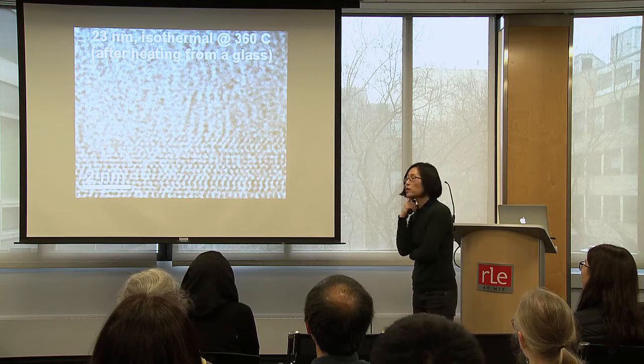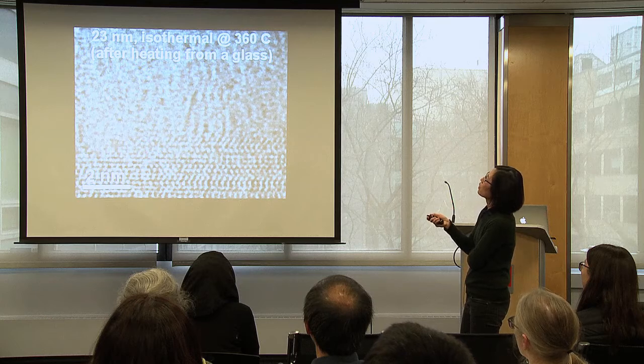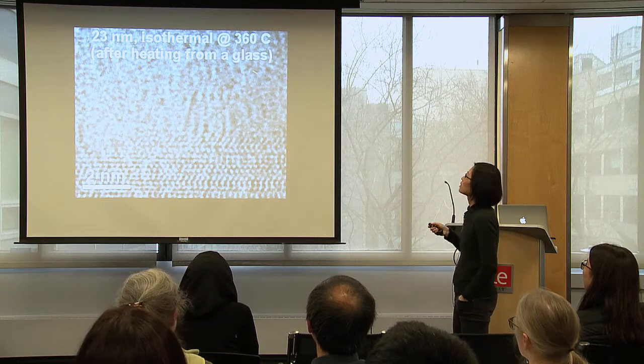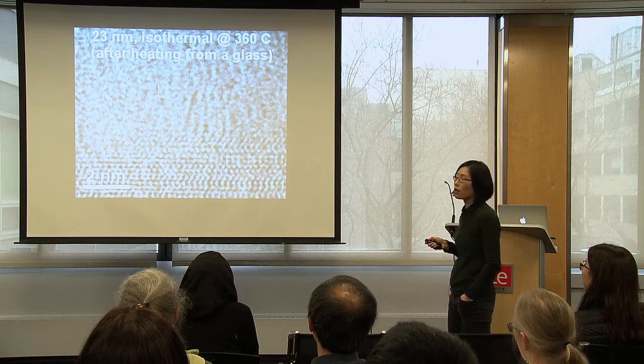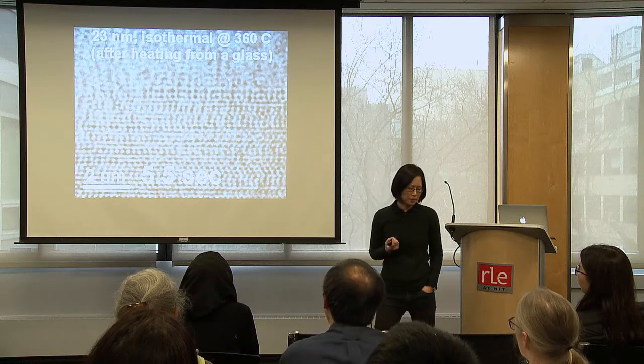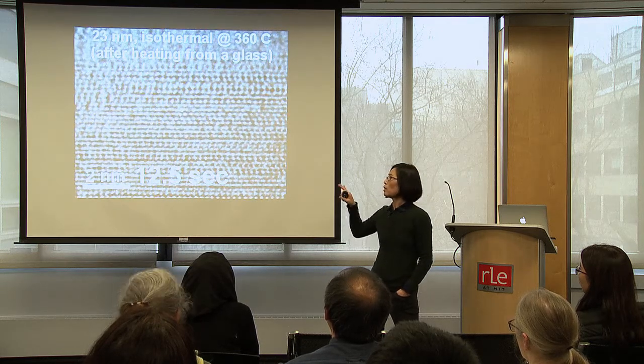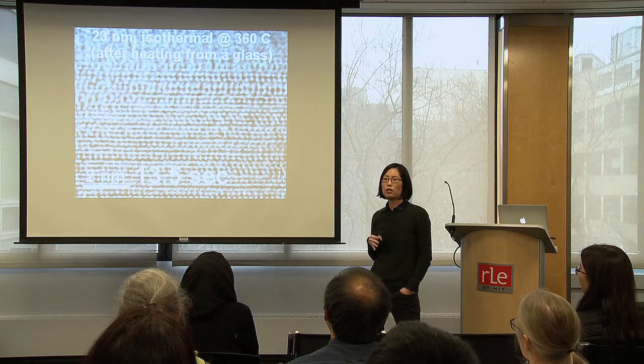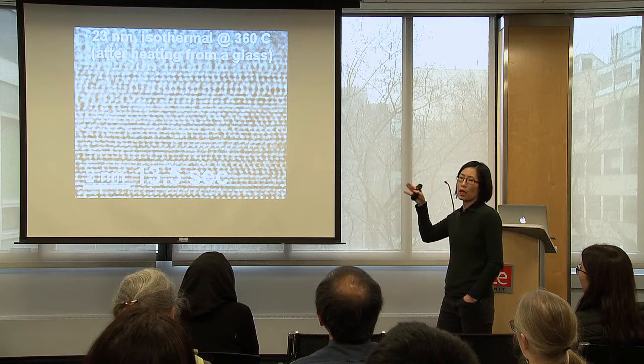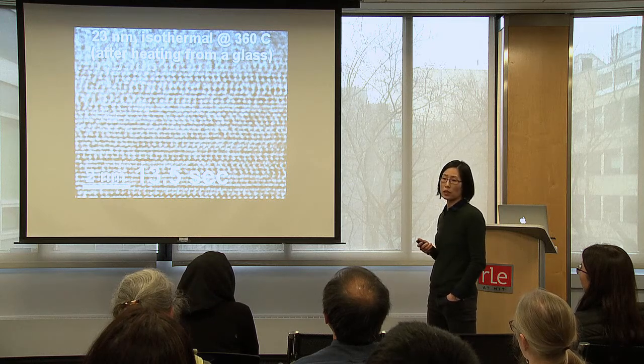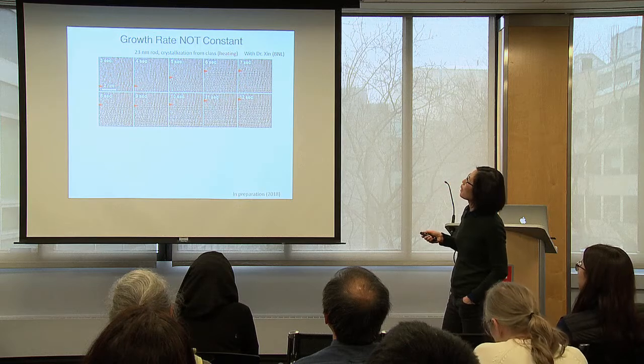So then that's when we went to Brookhaven National Lab to do aberration-corrected experiments. So here is a 23 nanometer rod. We're heating it from a glass state, sitting at 360 degrees Celsius. I'm zooming in into the middle of the rod. This is the amorphous state up top. Now we have the single crystalline grain, and then we're going to watch the grain growth, right? This is using the K2 detector. I think we ended up using a 500 frames per second frame rate. But to get the signal-to-noise ratio that gives you atomic resolution, we averaged 100 frames in post-processing. I think we can probably reduce that frame rate, but we felt that we were catching all the events necessary with 100 frame averaging.